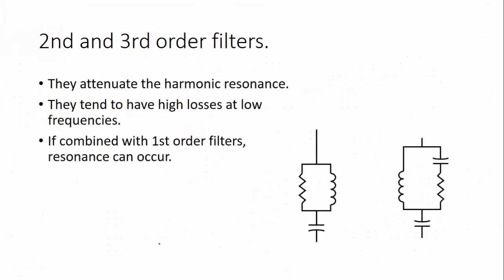So in order to fight this condition, there's an implementation of second and third order filters, which can include a resistance in series with capacitance, or a parallel combination of resistance, inductance, and a series capacitance, and they attenuate the harmonic resonance. The problem with these filters is that they tend to have high losses at low frequencies, which is exactly the thing that I want it for. I want this kind of filters for low frequencies.